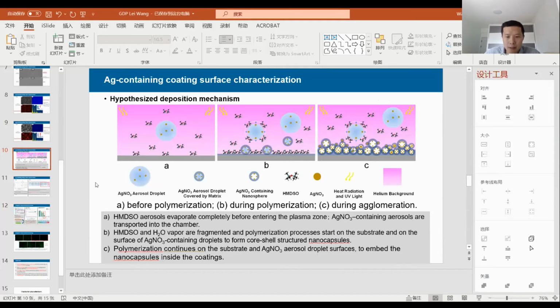With this technique, we can deposit core-shell structured coatings. As I mentioned, the two-phase release kinetics has an initial burst release, which we assume is the silver quickly released from the top surface of the coating. Do you see my cursor there? You can see that there are many silver particles, especially near the surface, which can be easily released, and this caused the initial burst release. And the long-term slow release is because of the silver embedded deep inside the coating.